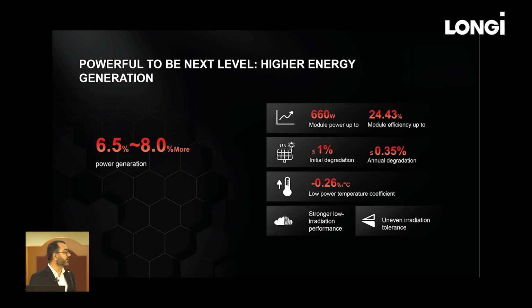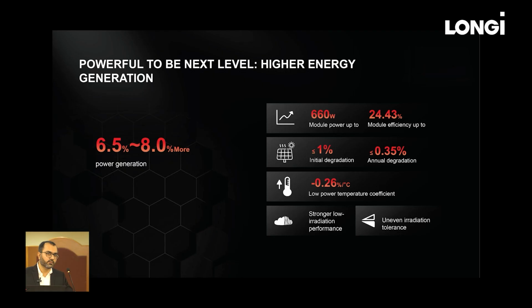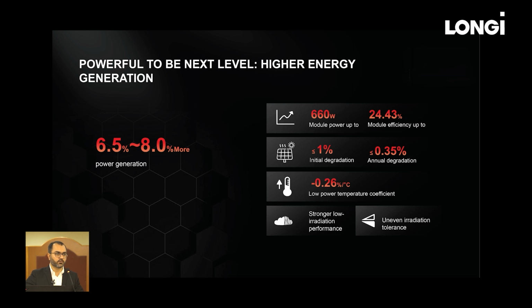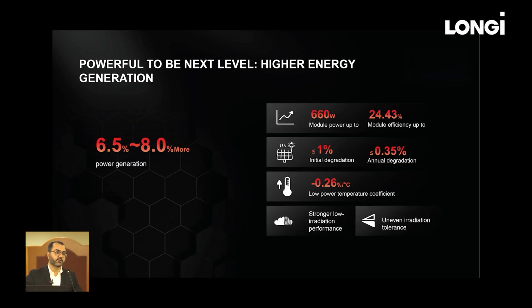This slide shows the summary of what you are getting with Hi-MO 9. Over the life cycle of the plant, you are getting about 6.5% more energy than the TOPCon. Obviously, it depends on the project as well. Sometimes some of the parameters of the site will not support, so this percentage can be lower. But based on the same size, we have increased the module power up to 660 watt, whereas TOPCon is currently standing at 620 and 625. Efficiency, as mentioned earlier, is 24.43%.